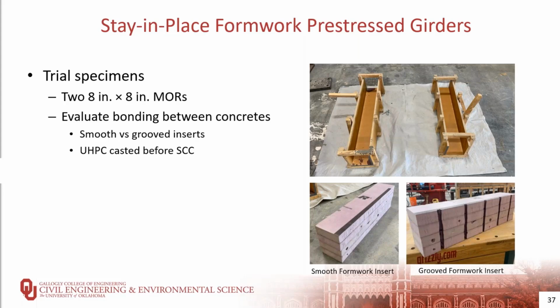And the reason why we wanted to investigate the bonding was that the UHPC was cast first, and then the pre-stress will have to transfer from the SCC infill into the UHPC formwork shell by bond between the materials. The order in which the concrete is cast is important, as usually UHPC is the concrete that is cast on the conventional concrete, not the other way around.